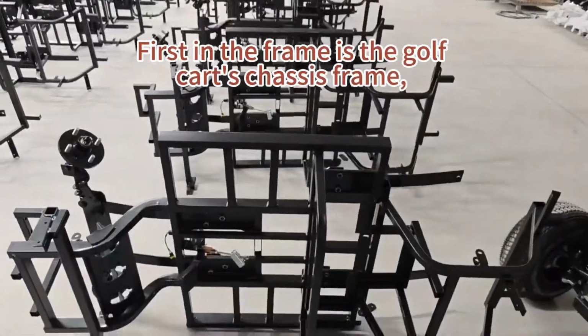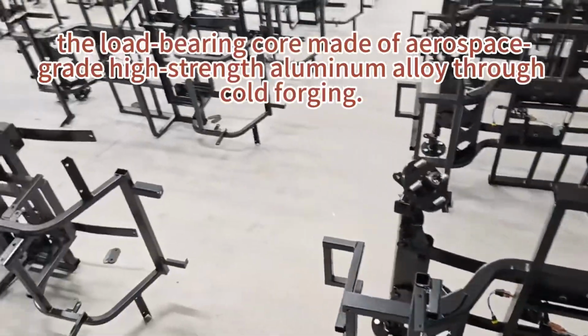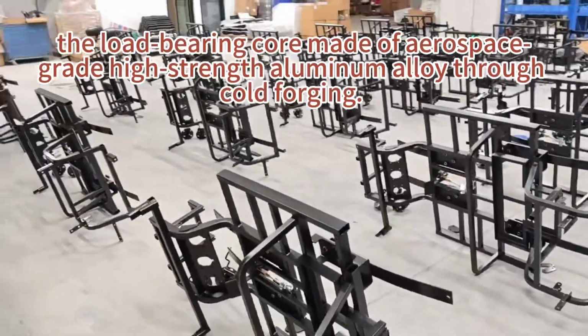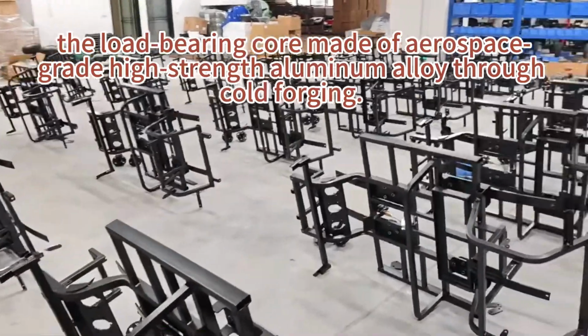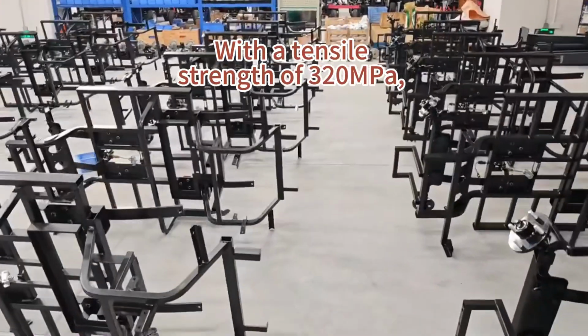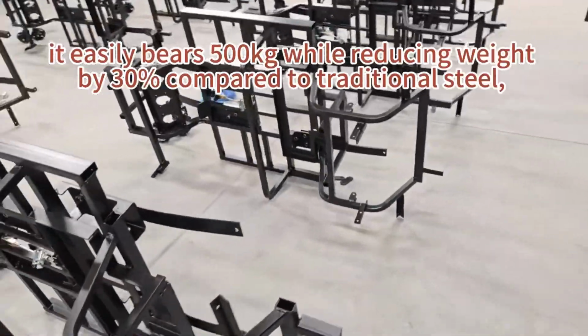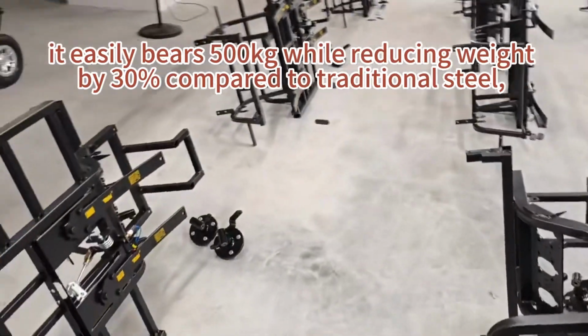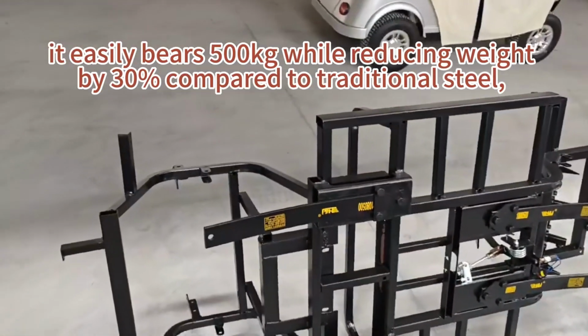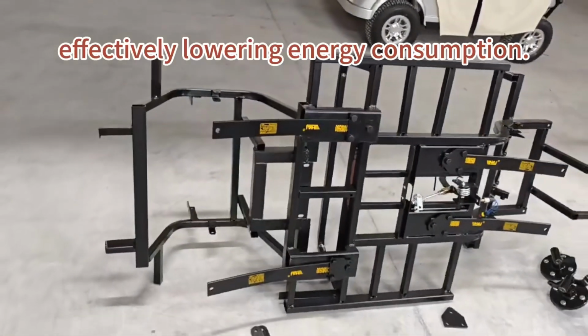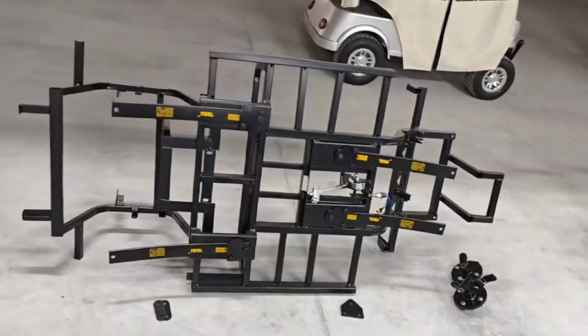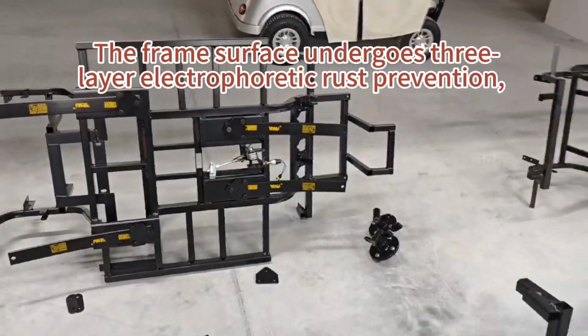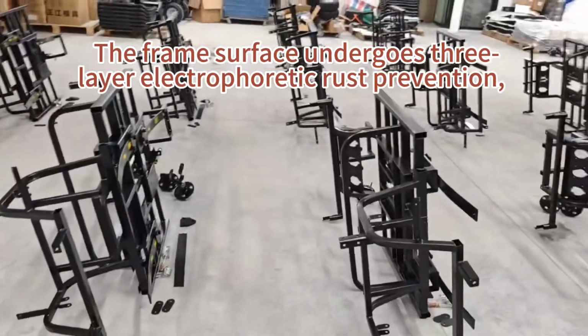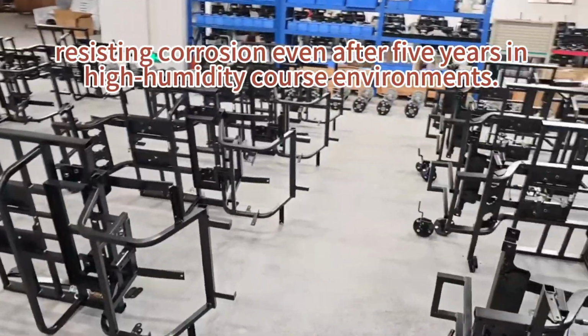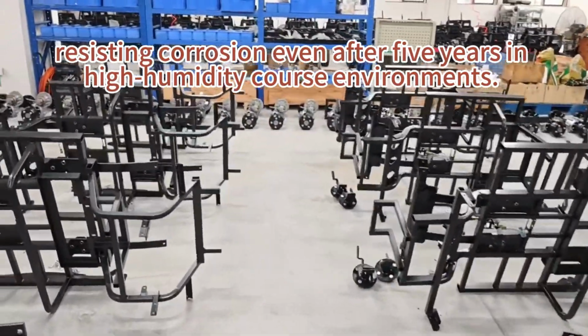First in the frame is the golf cart's chassis frame, the load-bearing core made of aerospace-grade high-strength aluminum alloy through cold forging. With a tensile strength of 320 MPa, it easily bears 500 kilograms while reducing weight by 30% compared to traditional steel, effectively lowering energy consumption. The frame surface undergoes 3-layer electrophoretic rust prevention, resisting corrosion even after 5 years in high-humidity coastal environments.